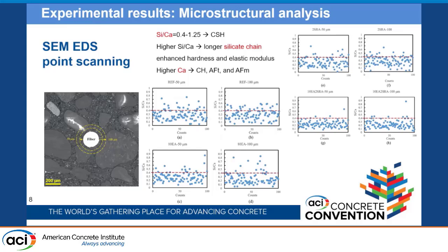I did SEM EDS point scanning in 2 strips, as you see on the left image, up to 100 micron away from the fiber, and 100 points in each strip were scanned.